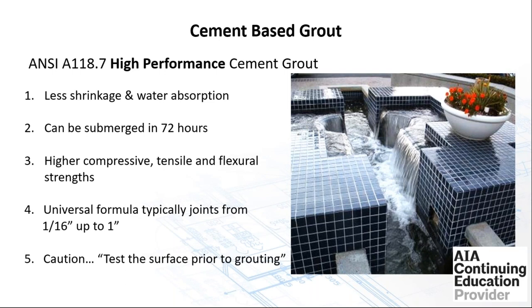A lot of times we think the epoxy is the best product to use, highly chemical resistant, or the industrial grade epoxy. Epoxies are very, very good. However, it's doing the research, knowing which product should be used in this application, what's best to be submerged in a short amount of time. Obviously, the epoxy is not the best in this installation. However, the 118.7 is not going to be the best in the back of a kitchen. So again, do your research, call the manufacturer, check the technical data sheet, just to know exactly which product to use in the installation that you're up against.